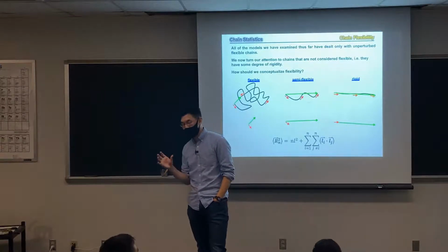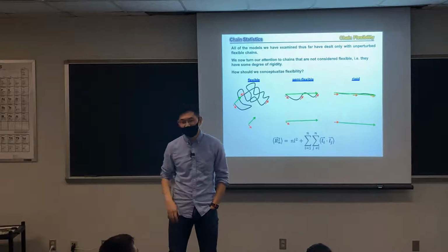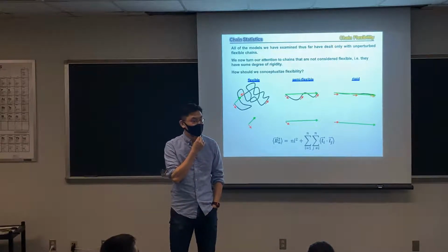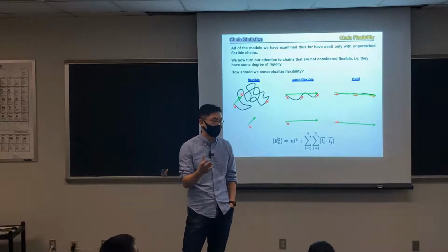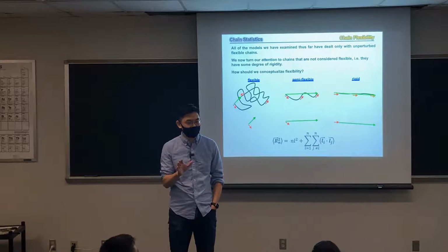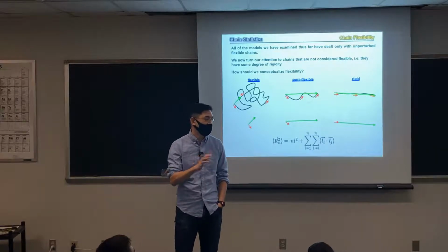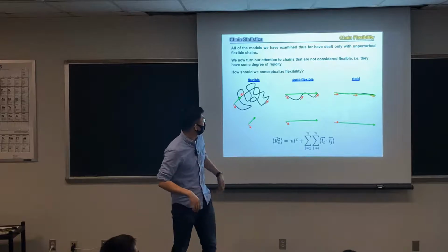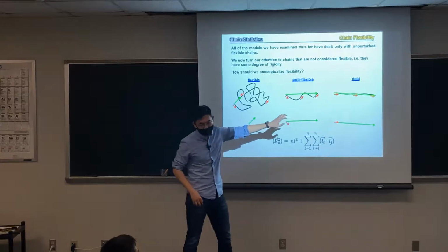It has a 5-member ring along the backbone, and you have LP of about 3 nanometers. So 3 or 4 times bigger than polystyrene, but not too high. So we call it semi-rigid, and we will cover it later. In the textbook, we actually call it a worm-like chain. So something like this, semi-flexible.